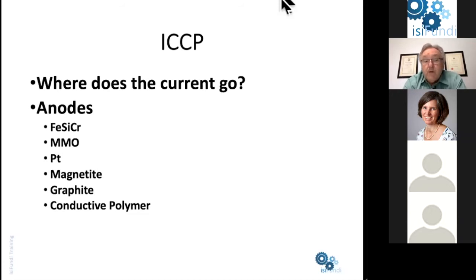One of them, the real long-term stalwarts of the industry, is what we call silicon iron, more often nowadays silicon iron chrome. These anodes corrode relatively slowly and provide us with 25, 30 years service life without any problem. However, they are heavy and somewhat difficult to use. The latest development over the last maybe 20 years or so has been the mixed metal oxide coated titanium anodes.